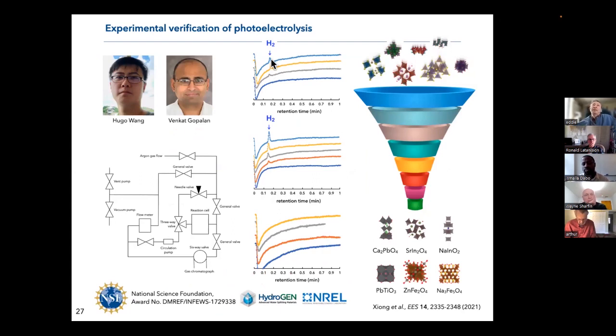So now comes the most important validation, gas chromatography, that enables us to detect with high sensitivity the generation of hydrogen. And here, our collaborators at Penn State, Dr. Gopalan and his group, have developed a specific setup that involves a closed cycle here. So essentially, there is a mode of operation where you can isolate the reaction cell from the rest of the environment and have a pump that is going to circulate and improve the sensitivity and the collection of hydrogen. And then what is very important is also to have a purging mode, essentially ensuring that between each test, you remove all of the hydrogen and all the residues. And this is achieved through this other mode of operation. So overall, this type of setup enables us to very sensitively and very accurately, without contamination, detect the presence of hydrogen.